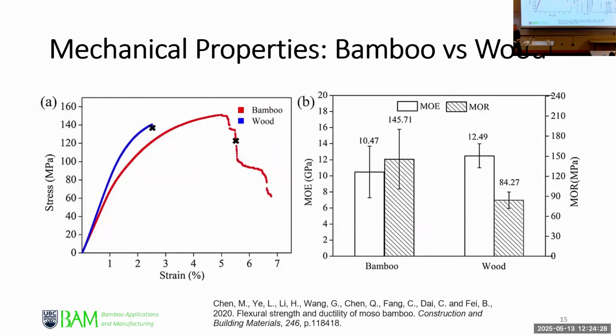So when it comes to engineering properties, and let's say building applications, we're concerned most about the strengths and then the elasticity. We do a simple bending test, like apply load and see how much load it can uptake, and how soft or rigid materials are in terms of elasticity. You can see bamboo is actually going higher into a maximum load, but mostly it goes through a longer deformation process before it fails, whereas wood is more rigid and brittle. And what that means is that the strength of bamboo is much higher than wood.